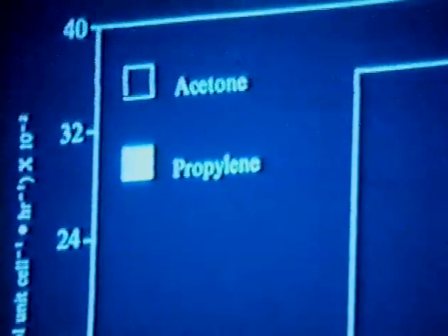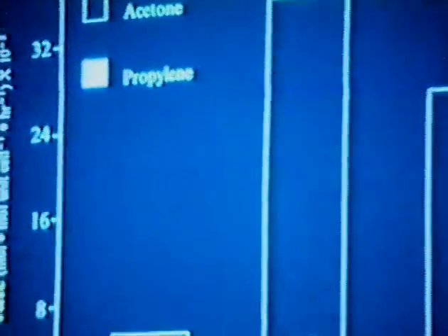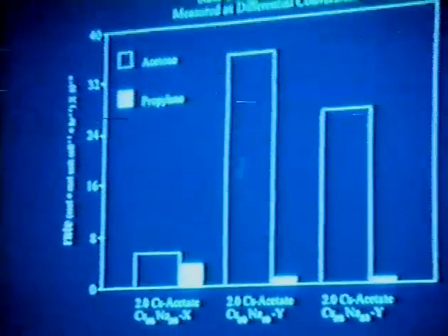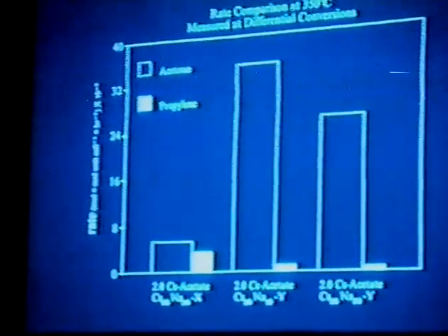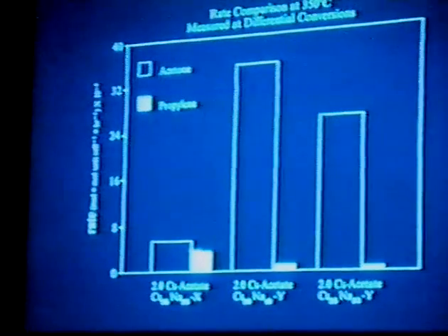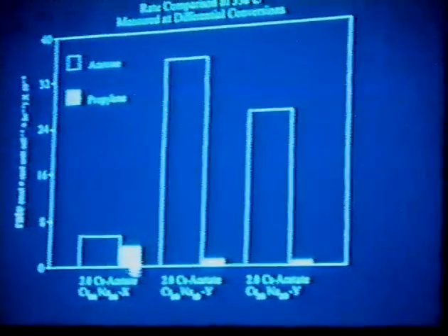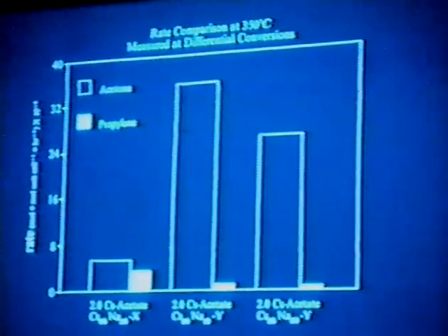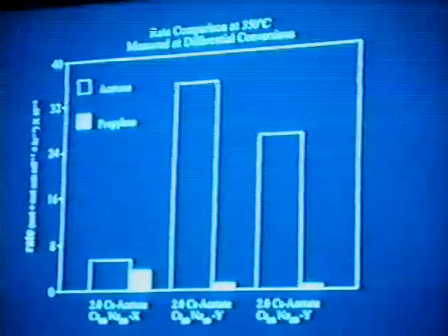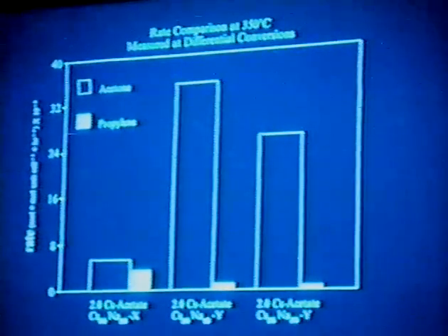It might further add that without impregnation, the activity of this material is comparable to the X, so it would only be up here. So all this other activity is presumably due to the impregnation technique. Another point is that the selectivity for this material is over 97%, whereas for the X material, it's only around 60%. And furthermore, the partially exchanged Y is active as well, suggesting that these sodium cations are in fact not exchanging during impregnation.